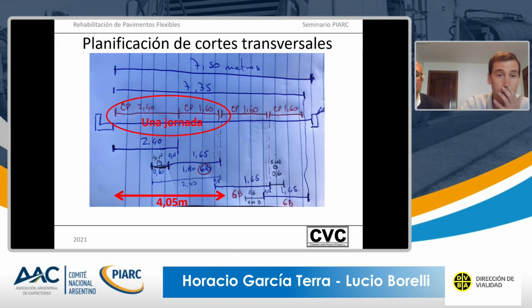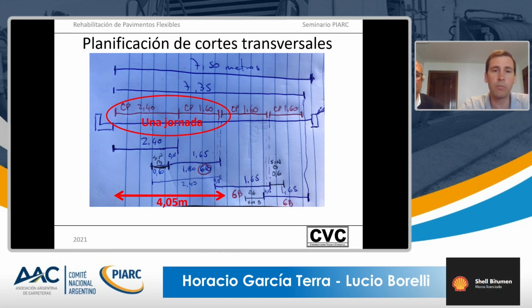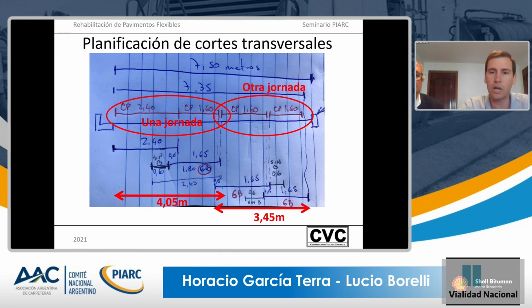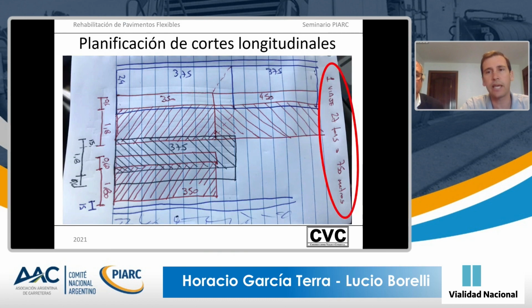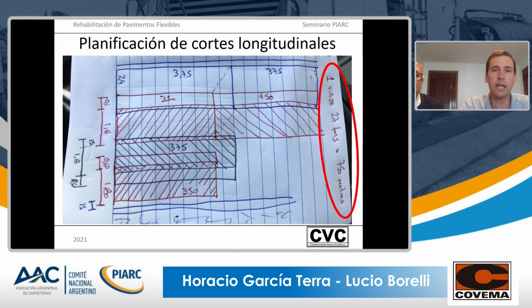many factors. And in the case of Road 102, on the first day we did the slow-speed lane, laying the Portland cement without lapping, because it's very important, because it helps to distribute the foam. But at least we need a 15 centimeter lap between cuts, not lapping the Portland cement, but doing a lap in the foam asphalt. As to longitudinal cuts, it is important to point out that we need to take into account the asphalt cement, and we cannot use up to the last drop of asphalt cement.